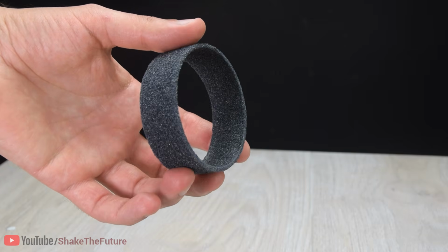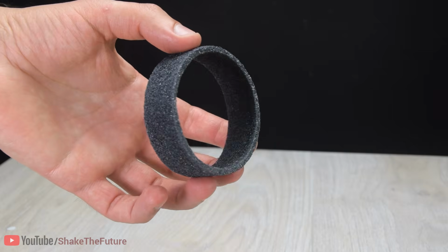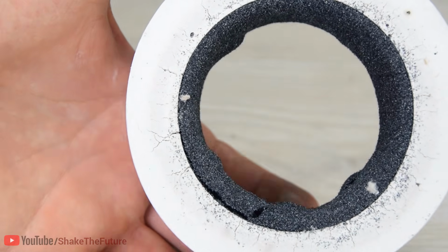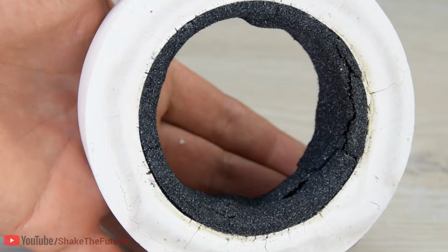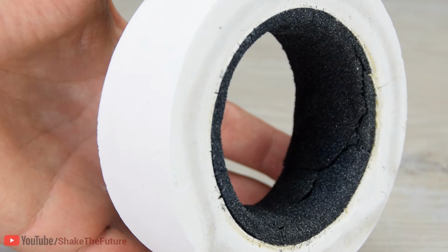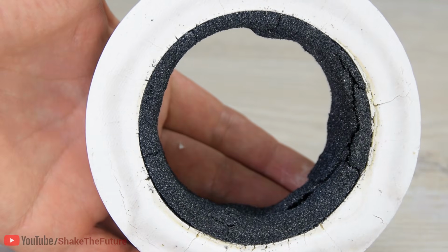It weighs about 40 grams and is 4 mm thick. Here's a failed ring with too much water glass. The water glass bubbled up and cracked the silicon carbide.